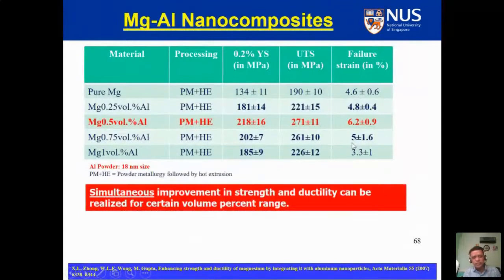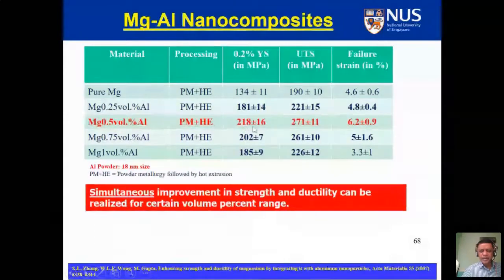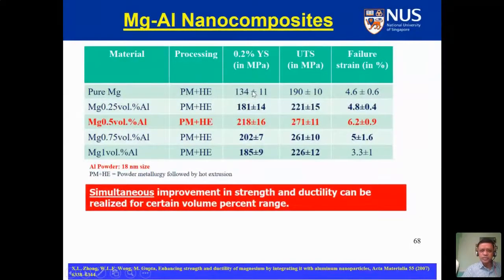So we used the magnesium aluminium nanocomposite to show the unique capability of microwave, that how fast we can do it. And we put just 0.5 volume percentage of aluminium. If you just focus on the red fonts, you will see that we are improving on the strength, whether it's a yield strength or a UTS, and also the ductility. So basically, provided you put the right amount of the nano reinforcement, you can have the simultaneous improvement in the strength and ductility, which cannot be realized by any other length scale of reinforcement for ceramic particles or metallic particles.